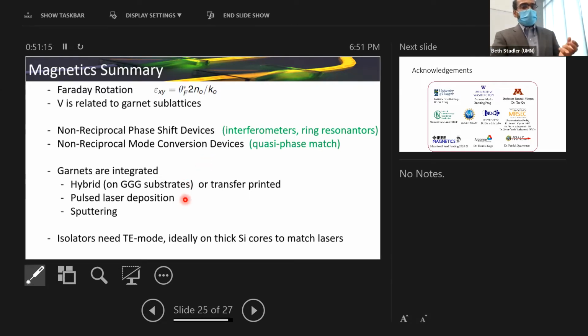Lastly, we saw a couple of different ways of integrating garnet. It can be hybrid, heterogeneous, transfer printed, and the garnet can be grown either using LPE, pulse laser deposition, or sputtering. We realized that isolators need TE mode to operate, which is convenient as the lasers are also TE mode. Thicker core silicon waveguides are preferred because that allows us to integrate it before the light sees any tapers or couplers before moving further into the photonic chip.